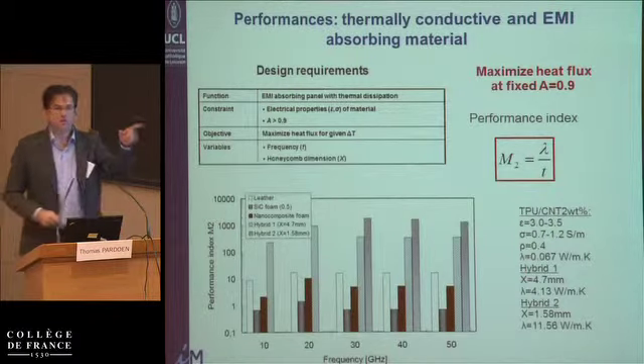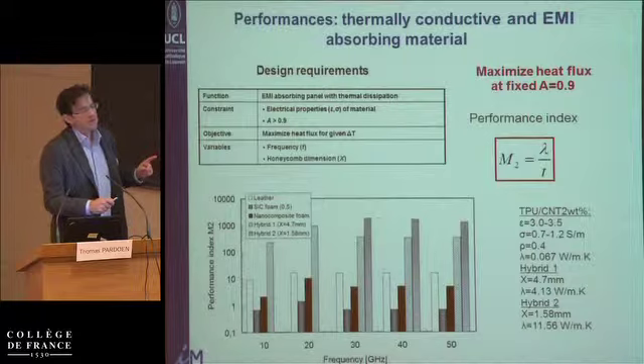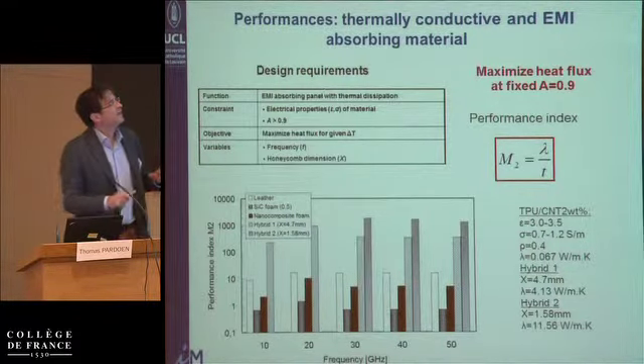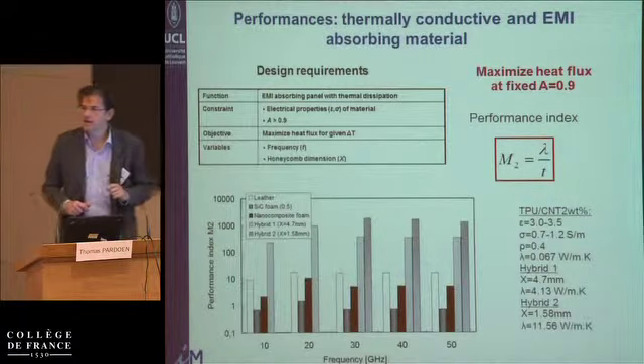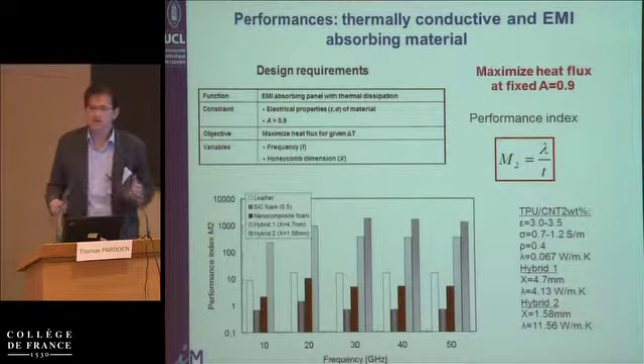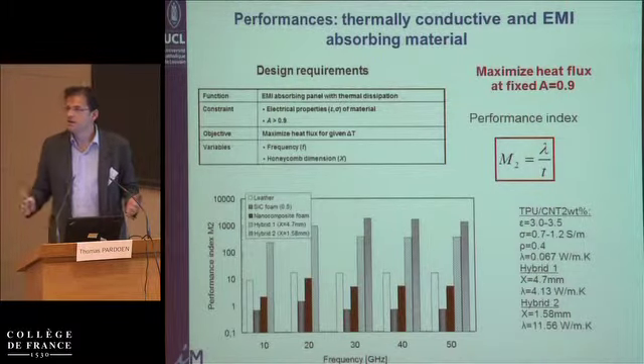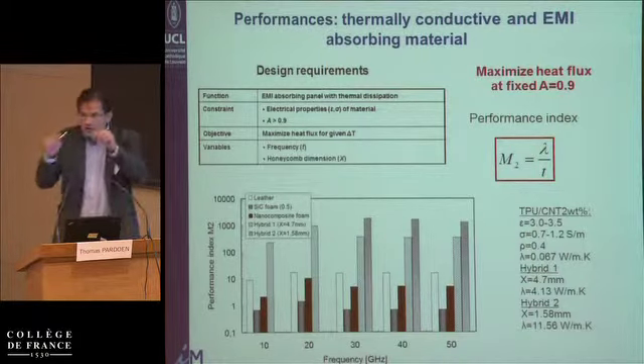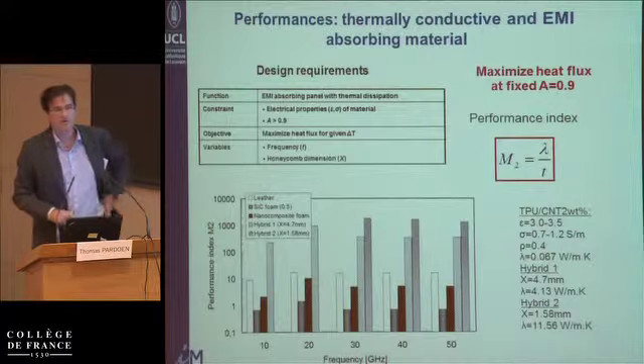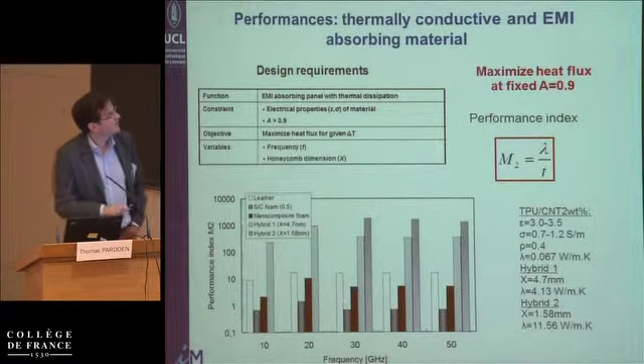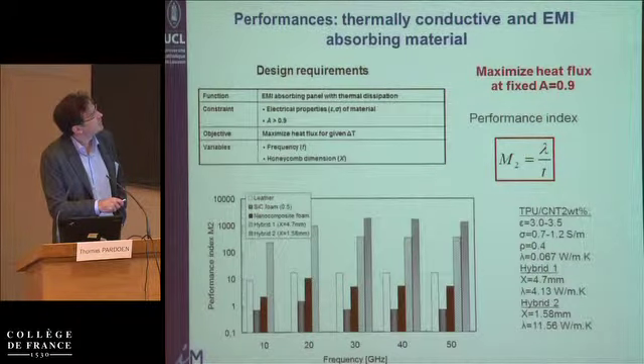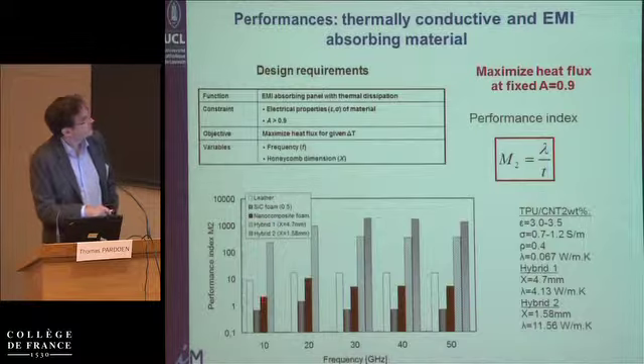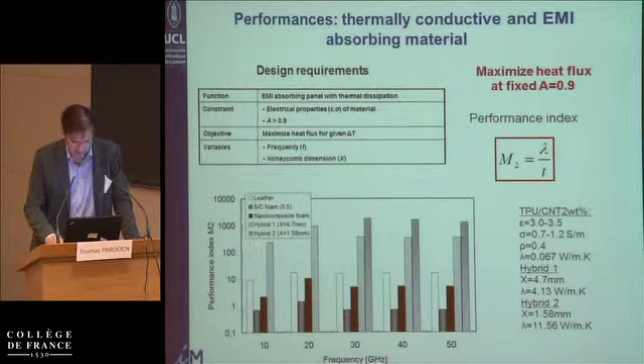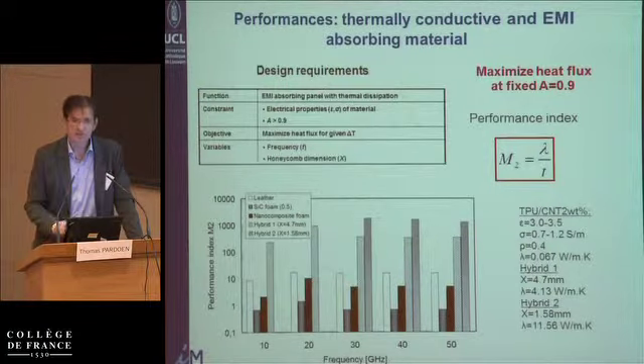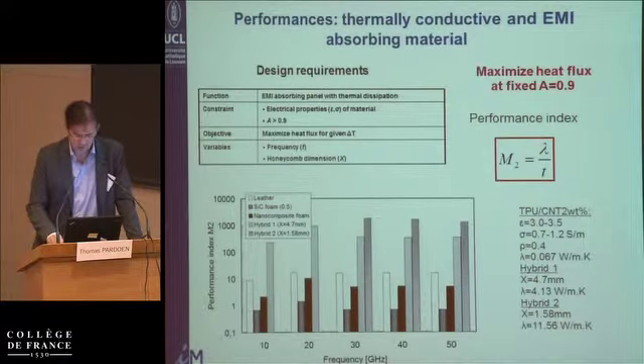So for every material, you look at the dielectric constant and electrical conductivity, and in order to reach an absorption of 0.9, you will get a value of the thickness. As a matter of fact, for most materials, the thickness will be infinite because they have no absorption capacity. There is a narrow set of materials for which you will have a value of the thickness, and this is a comparison of the performance index for different materials, the leather, silicon carbide foams, and so on, compared to our hybrid materials. And the material is doing a fairly good job to optimize the performance index, even if it's not the best application here, because it's more thermally insulating than thermally conductive.